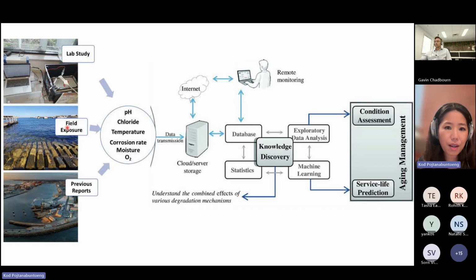The last slide is basically to show that to address such a complex and long-period phenomenon, we employed a combination of different approaches: the lab study, field exposure (this one is the old samples Tasha showed before, but the one that we presented is also just next to it), and previous reports. So we need to employ multiple aspects of the data that we can gather, in this case from 3 different locations, and build the database to make sense of all the trends in the data, to help the asset owner predict the diffusion of chloride. By ensuring that we have robust data that can be fed into the system, we know that the prediction can be robust and reliable. That's pretty much what I have.